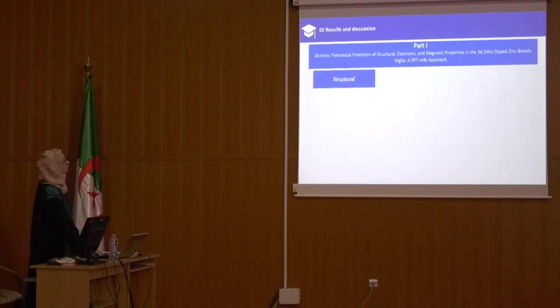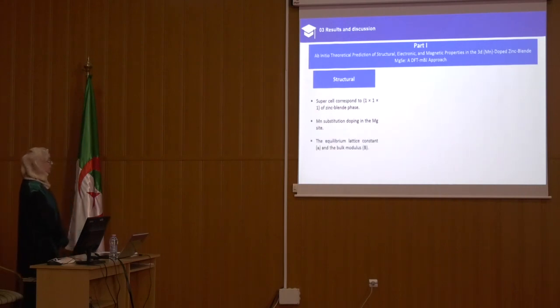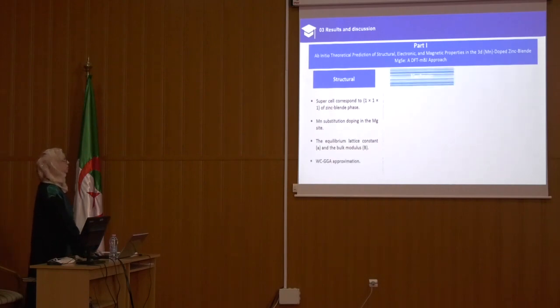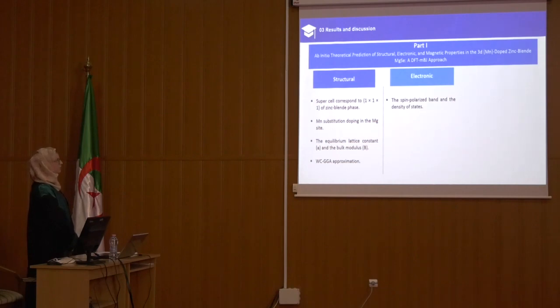So first we have structural properties by using a supercell of 8 atoms of zinc blende. We choose manganese as substitutional doping in the Mg site to calculate the lattice parameter and the bulk modulus by using the WC-GGA approximation. For the electronic properties, we calculate the spin polarized band structure and the total and partial density of states by using the TB-mBJ approach to solve the problem of underestimation of the band gap.